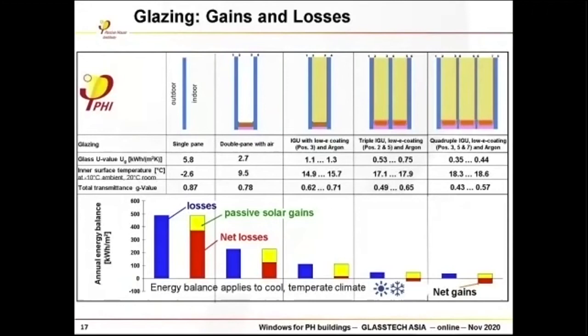Well, and the basic quality is maintained so far by insulation, to have several window panes. And a good compromise for most climatic regions is a 3-pane glazing with 2 coatings on number 2 surface and number 5 surface, and with a noble gas filling inside, and a very well designed glazing rebate. For very cold regions, you may go down to a 4-pane glazing, but this is just for Russia and somewhere.